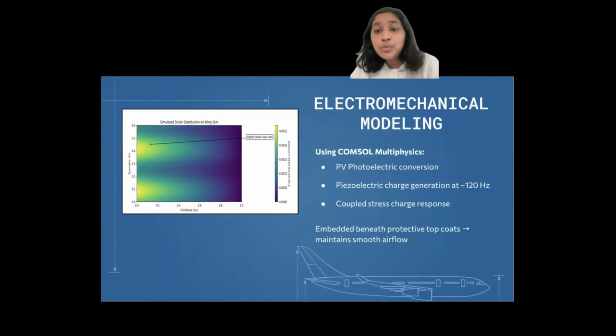Next, I used COMSOL Multiphysics to model electromechanical coupling in the barium titanate layers and simulate photoelectric behavior in the PV films. I analyzed how efficiently the piezoelectric layers could harvest vibrational energy across the resonance center near 120 Hz, a typical frequency for cruise-induced aeroelastic vibration. COMSOL allowed me to simulate charge generation, mechanical stress distribution, and electrical output under dynamic loading, essentially letting me stress test the nanostructures without a lab.